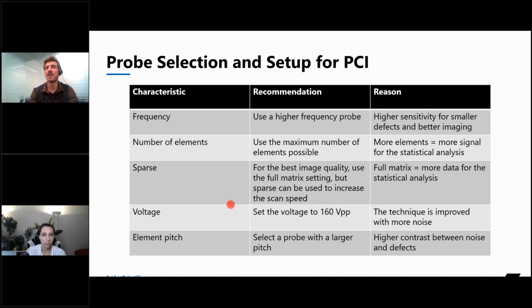For sparse, obviously the best image quality comes with full matrix, just like with regular TFM. But when scan speed is the priority, we can use the sparse to improve productivity. Also with the same idea, we want to have as much sound going to the part as possible. We want to crank the voltage up to the highest level. So on the OmniScan X3 64, that's up to 160 volts peak to peak. And the element pitch, we want to use a larger element pitch for our probe. So we're gonna have some comparisons later that show an A32 versus an A31, and there is a difference between the slight change in element pitch between these two.